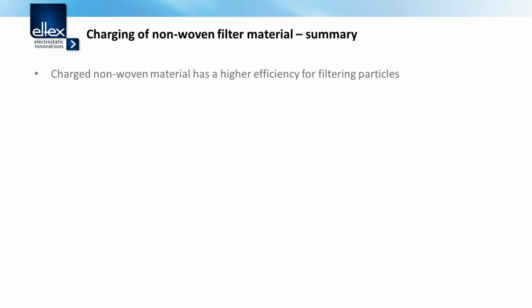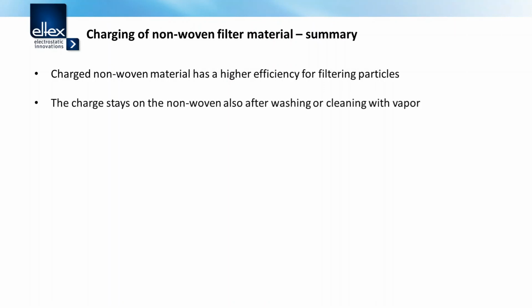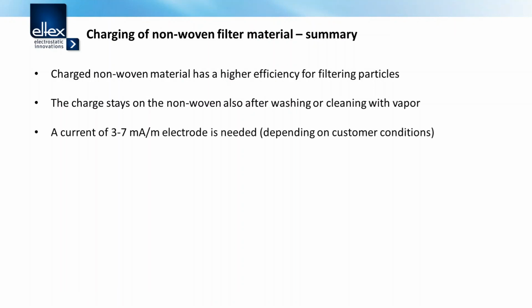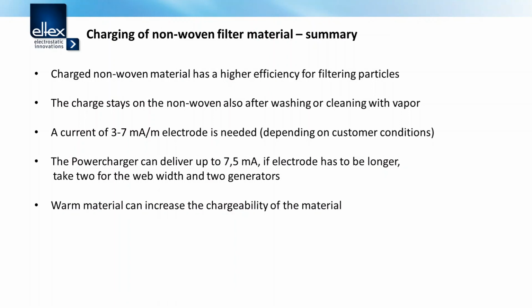So now the summary. Charged non-woven material has higher efficiency for filtering particles. The charge stays on the non-woven also after washing or cleaning with vapor. A current of 3 to 7 milliampere per meter electrode is needed, depending on customer conditions. The power charger can deliver up to 7.5 milliampere. If the electrode has to be longer, take 2 for the web width and 2 generators.